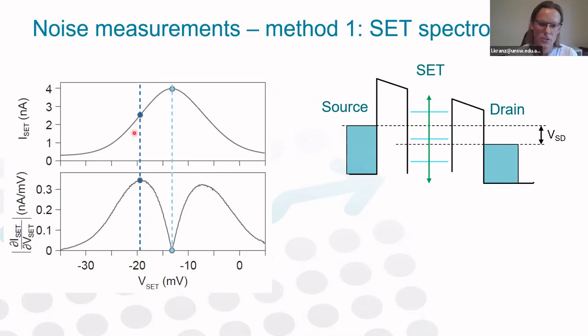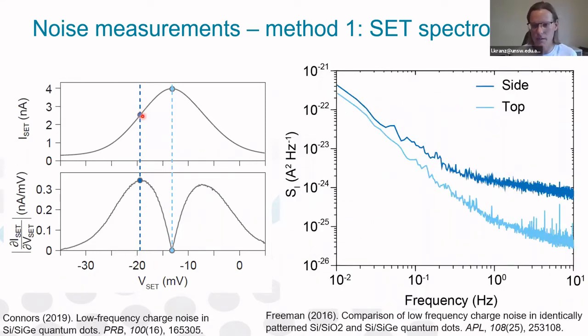So by setting the voltage to the side of the peak, we acquire a time trace. Basically, we record the tunneling current as a function of time, and then we calculate the corresponding power spectral density of these current fluctuations. This is shown here on the right. The dark trace corresponds to the data taken on the side of the peak, and we can obtain this power spectrum. And for comparison, we take a similar data set, but taken on the top of the SET peak. On the top of the peak here, we have high tunneling current, but the fluctuations in current are smaller because this tunneling current is less sensitive to any changes in electrochemical potential. And this reveals itself because this light blue trace taken at the top of the SET peak is actually lower. So it means that the fluctuations in current are actually smaller on top of the peak.